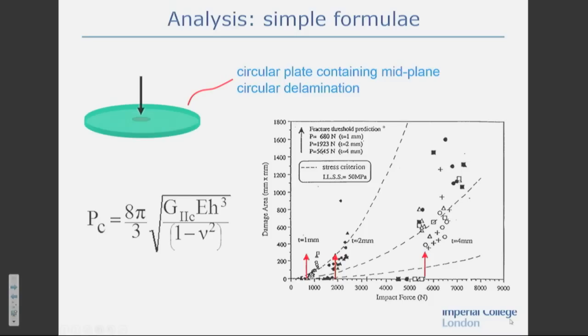This is quite an old set of data from tests done at Imperial College. This is damage area produced during impact testing. Plotted across the bottom is the magnitude of the impact force, the maximum impact force during the impact. The experimental data is all the discrete points you can see, first of all for 1 millimeter thick plates, and then 2, and then 4. The data has an interesting characteristic for each of these. Initially, for low energies, you get no damage, and then suddenly you start seeing damage. So that's the case for 1 millimeter. For 2 millimeters again, no damage for a while, and then you reach a threshold and you start seeing damage. And finally here, no damage, and then suddenly, when the force gets large enough, we see damage.